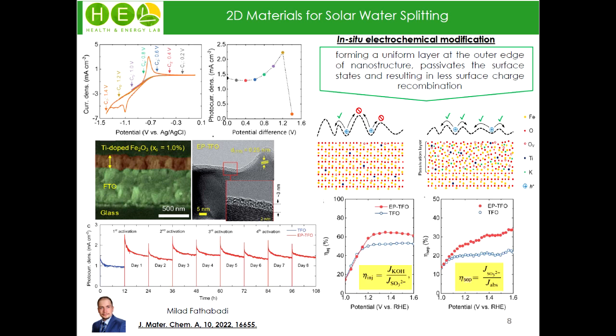You know that surface potential fluctuation may hinder charge transfer on the surface. So such modification could decrease this fluctuation, which is beneficial for the OER reaction on the surface.